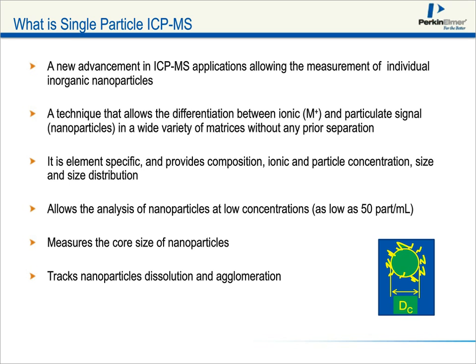It is a technology that's going to be measuring the core size of the nanoparticles. So it's a mass-based technology. It does measure the core size. It does not measure the hydrodynamic diameter, so it does not measure the overall size. It's really concentrated on the core size. And it is a technology that allows us to track the nanoparticle dissolution, because it has the ability to look at both fractions, ionic and particulate. And we'll be able to track agglomeration as well.